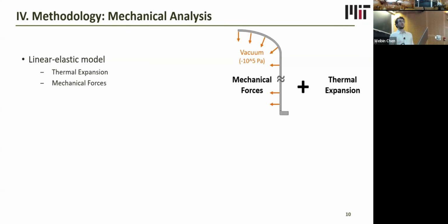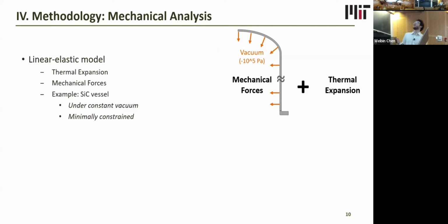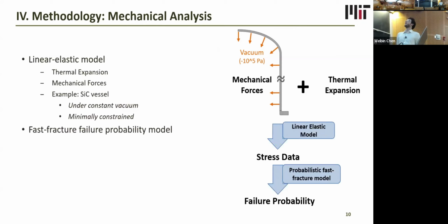So for our mechanical modeling, we take a pretty simple approach of just using a linear elastic model that accounts for both thermal expansion and mechanical forces. In the example that I'm going to show, we're assuming just the silicon carbide vessel is modeled. It's under constant vacuum and it's minimally constrained. What we then do is we take our stress data and we put it into a fast fracture failure probability model, because we're using a ceramic here, and ceramics don't necessarily fracture at one given stress value.